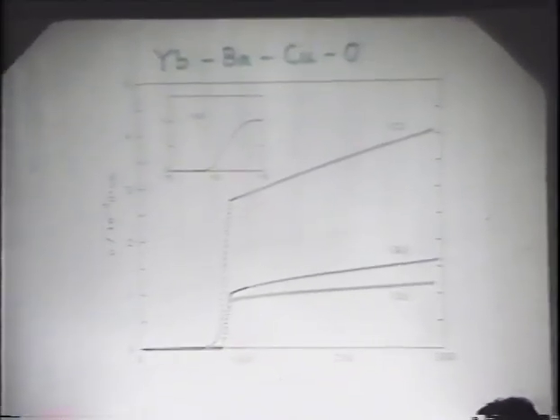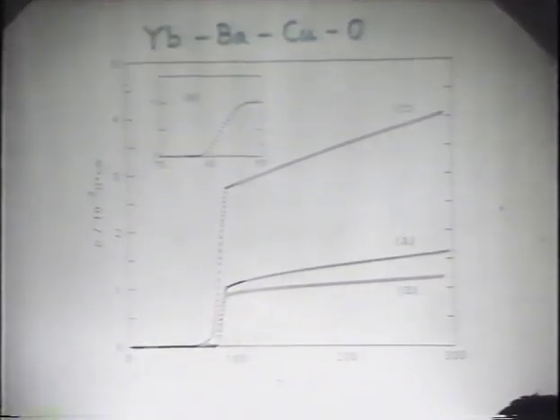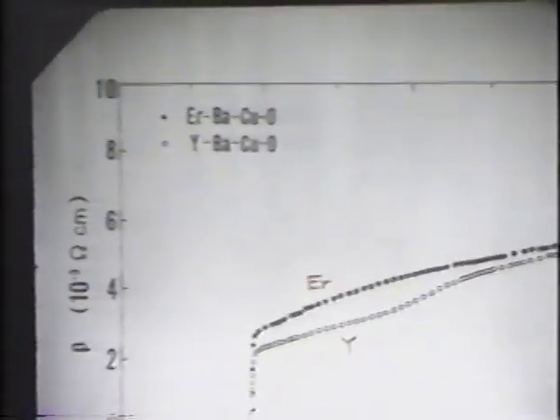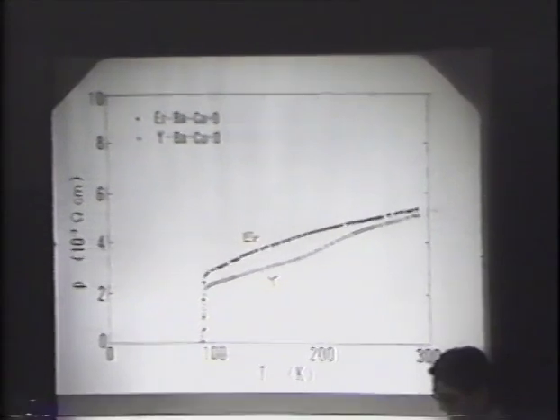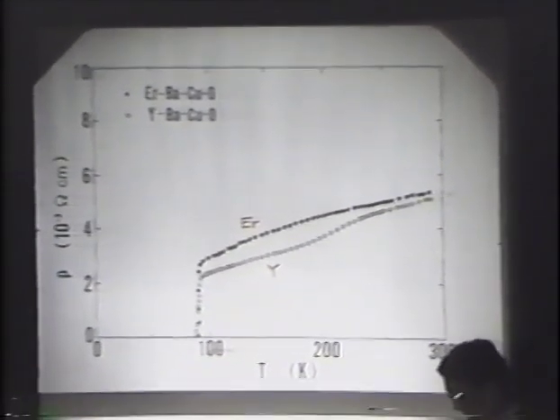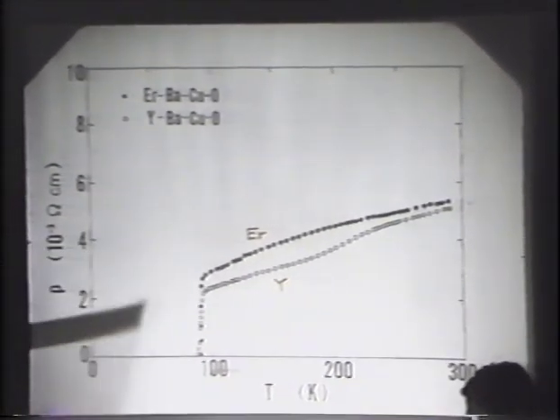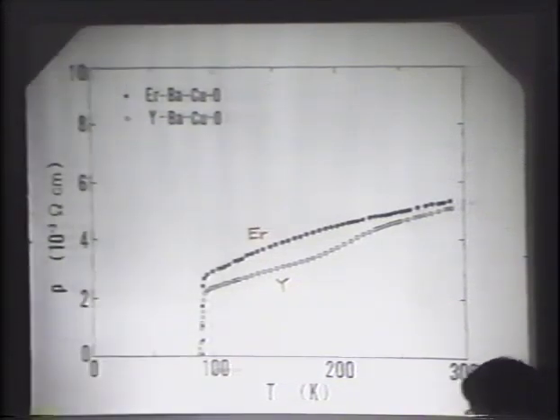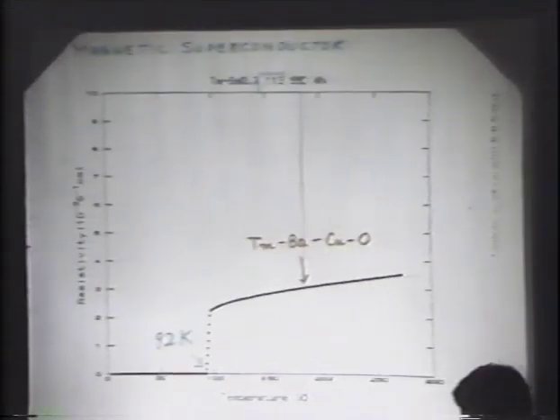Now we proceed to new materials which were found by Japanese groups. We replaced yttrium by other lanthanoid elements such as ytterbium, erbium, holmium, and dysprosium, and found that all of them showed a high TC of 90 degrees Kelvin. They have the same X-ray pattern as yttrium barium copper oxide. I will show you some of the data as follows. Yttrium, erbium, dysprosium, and so on.